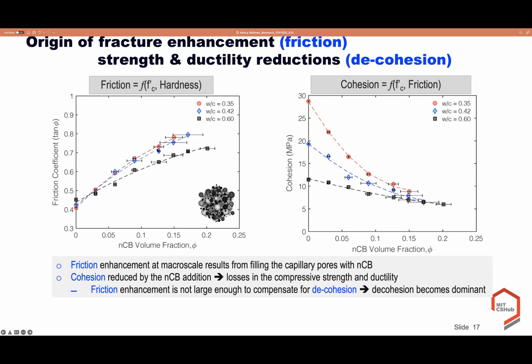And also what we observed is that there isn't any difference between the two water cement ratios, 0.35 and 0.42. This confirms that because 0.35 is less than the stoichiometric level, there are no more pores to accommodate nanocarbon black particles. And this proves that the enhancement of the friction coefficient results from filling the capillary pores with nanocarbon black particles. While we see a de-cohesion of the matrix when adding the nanocarbon black particles, and the friction enhancement is not large enough to compensate for this de-cohesion, so the de-cohesion becomes dominant.